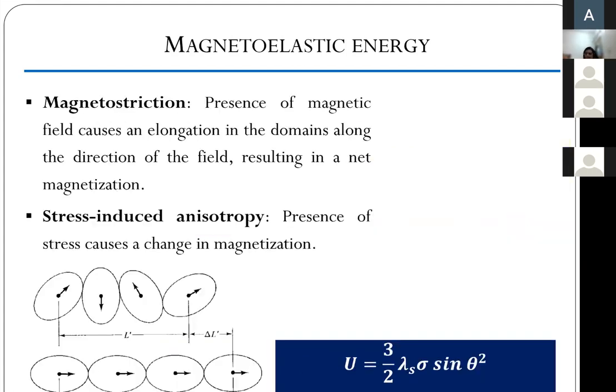Then magnetoelastic energy. This is the most important one when we talk about coupling. This term incorporates two effects. One, magnetostriction, where the presence of a magnetic field will cause elongation. One can see what is happening to the domains. Each domain is marked with a certain shape and an arrow. The arrow is the direction of the magnetic moment within that domain. As we apply a magnetic field, all the domains orient themselves, and in the process end up causing an elongation. So this is magnetostriction. This is a pictorial depiction of that.